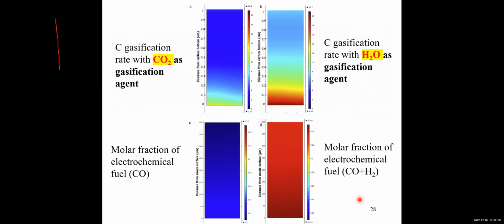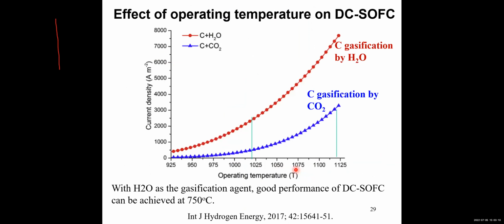Then we used a multi-physics model to understand why. We found that using water for carbon gasification, the reaction rate is much higher than using CO2. Also, the concentration of fuel available for the electrochemical reaction is much higher. If you look at the different corners, the difference is very significant.